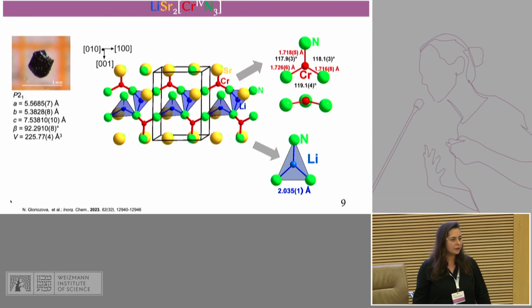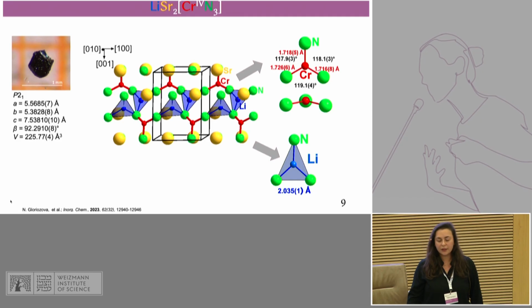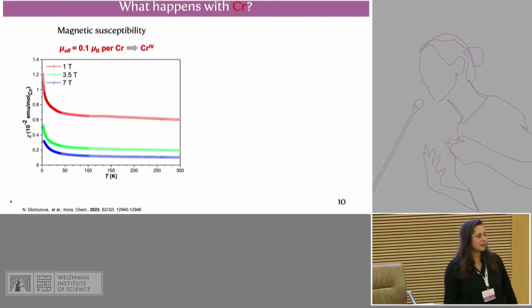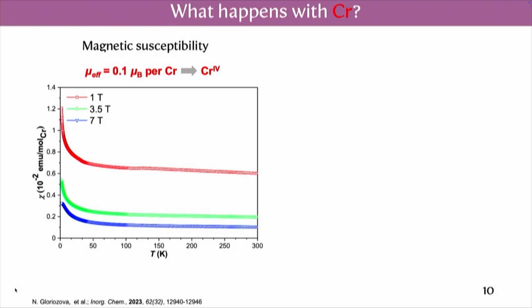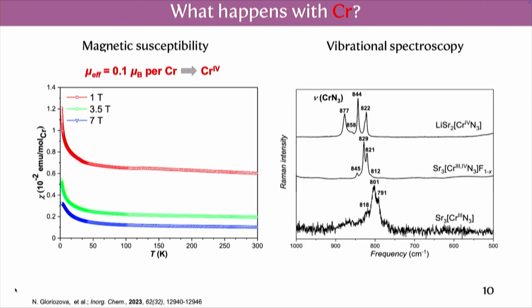To know if this compound can be used in batteries, we need to understand the oxidation state of chromium. For that, we measured magnetic susceptibility. From the effective magnetic moment of 0.1, we established chromium-4 in this structure. To prove that, we also used vibrational spectroscopy. We measured our compound and two compounds as standards, where we know the oxidation state of chromium, and from the shift to higher frequency from the standard compounds to our compound, we proved that the compound has chromium-4.